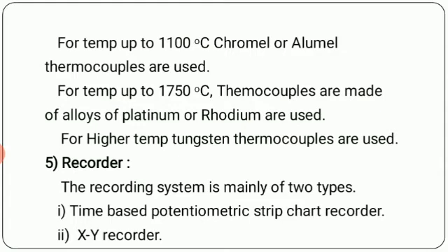For temperatures up to 1750 degrees Celsius, thermocouples made of alloys of platinum or rhodium are used. For higher temperatures, tungsten thermocouples are used.